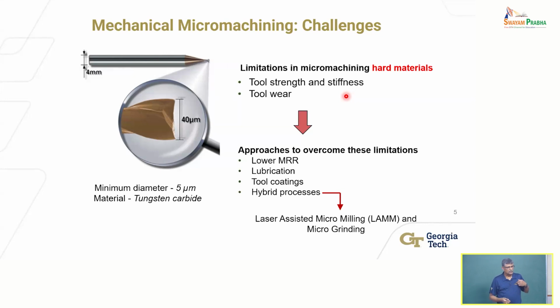But what's the challenge? Tool strength is a challenge. Now, if you're machining soft materials like polymers or very soft metals, then it's less of a challenge. But if you're machining something difficult, you want to make micro scale features in titanium. The biomedical implants, many of them are made out of titanium, chrome alloys, and other types of compatible materials, and therefore those strong materials. They're strong both in terms of high temperature strength. They also tend, so that makes them difficult to machine or to cut. So stiffness can be an issue as well.